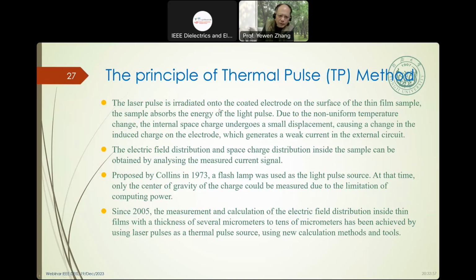The laser pulse is used here, also using a laser on the coated electrode on the surface of the thin film. As the sample absorbs the energy of the laser, the temperature changes. For example, from the laser side the temperature increases, but the other side is cold. So the internal space charge has a small difference. Also with the thermal expansion the temperature increases a little bit, so the charge moves a little more. This causes a change of the induced charge in the electrode, which generates a weak current. The electrical field distribution and spatial distribution inside the sample can be obtained by analysis.